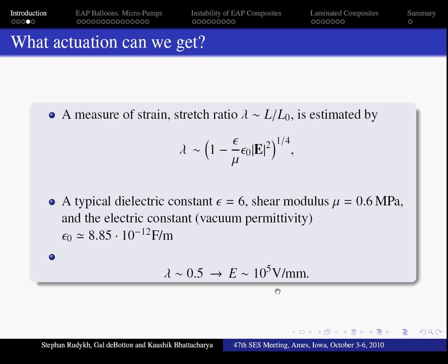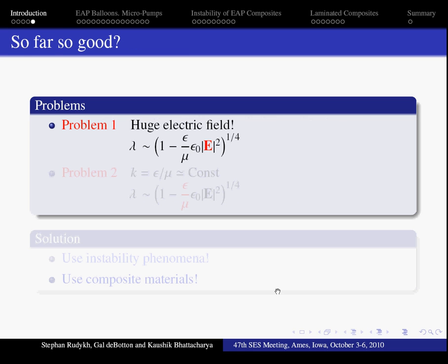So this is the major problem, huge amount of electric field that we need. Maybe we can compensate the electric field by taking a material with higher ratio between dielectric and elastic constant. Unfortunately, this ratio is nearly constant from material.